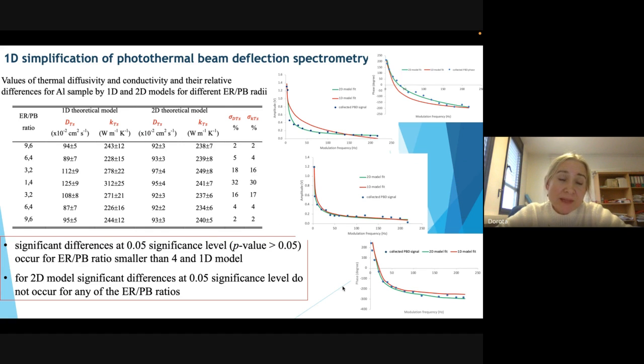So we would like to know if it's possible to simplify our 2D theoretical model to 1D. So we did the analysis for a chosen sample with known thermal properties. The chosen sample was the aluminum sample, for which the thermal conductivity and diffusivity are very, very well known. So we measured the signal as a function of modulation frequency, but for different ratios of the excitation and probe beam radius. So we got the values of thermal conductivities and diffusivities in case of using the 1D model and the 2D model for different ratios of excitation and probe beam radius.